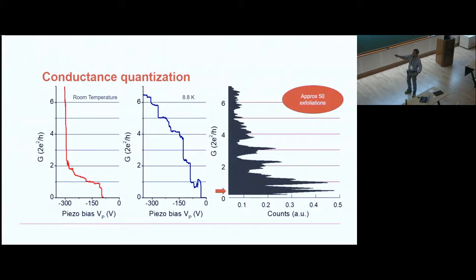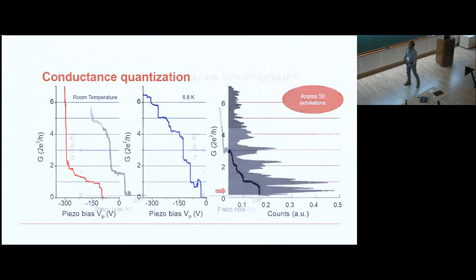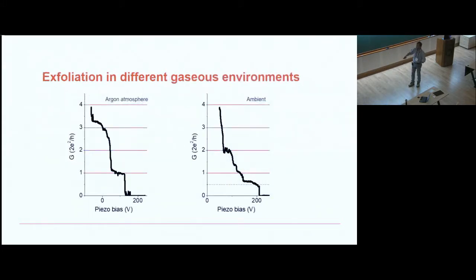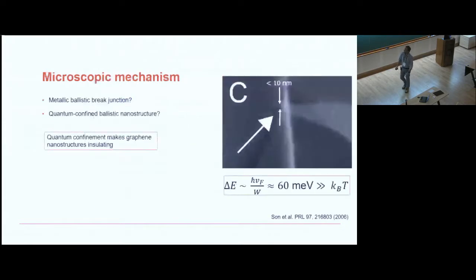Before that, as I said, it's a statistical experiment, so we did it a large number of times and see where you get most of the conductance plateaus. And this strong histogram at 2e square by h shows that in these systems of exfoliated graphene nanoflakes, you end up getting universal conductance just before the system breaks out, okay? All right, so this happens in all cases in different gas atmosphere, etc. We will not go into that detail.